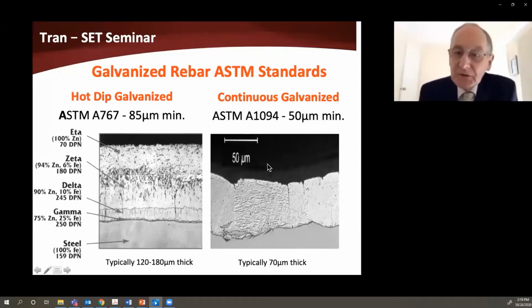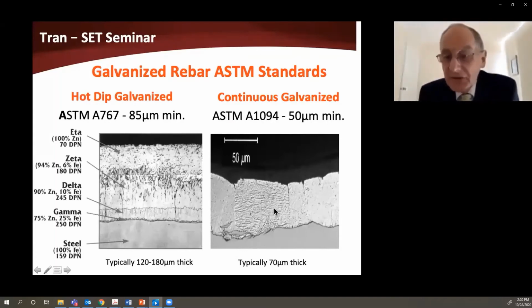Now, with continuous galvanizing, 1094 is the relevant standard. That has a requirement for a 50 micron minimum thickness on the coating. And here's a typical micrograph of that. Now, these coatings typically get up to about 70 microns thick, but this is basically a 50 micron minimum thickness coating, which is essentially equivalent to what is here on the outside of the bar on a bright coating. The difference is, of course, here that because of the very short time that the bar is in the